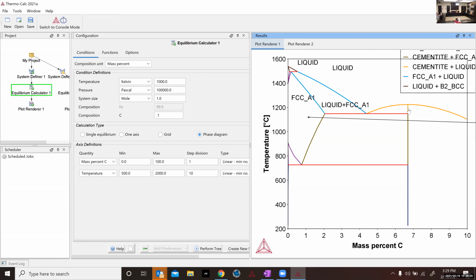And so when this line compound comes straight up to the liquid at this specific composition, which is at 6.7 weight percent carbon, which happens to be, without having to do the math, Ethan, what do you think 6.7 weight percent carbon is in atomic percent? If we have 3 iron atoms for every carbon atom, the carbon content has to be 25%. 25, 75, 3 to 1, right? Yes. Okay, sure.